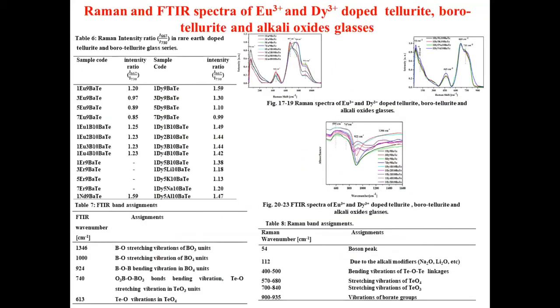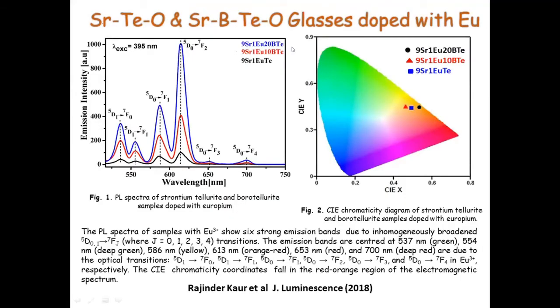We can determine the short range structure by Raman and by FTIR spectroscopy. We can see how the coordination number of tellurium with oxygen changes when you increase the metal oxide concentration by measuring the relative intensities of the Raman bands at 650 and 750 cm^-1. Strontium tellurite is a very good material for hosting the europium ions. And this is some of our other work.